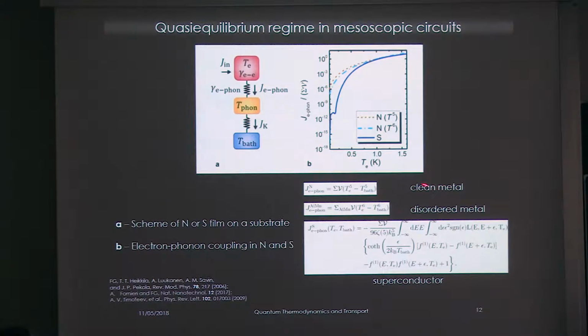Depending on which kind of metal we are using, there are some very well-known power laws. This heat current, for instance, is plotted here as a function of the temperature. The yellow one is the behavior for a clean metal, which goes like T to the 5th power. For a disordered metal like aluminum manganese, for instance, this goes like T to the 6th power. A typical clean metal that obeys this law is silver or copper. Polycrystalline films of copper or silver obey T to the 5th power.